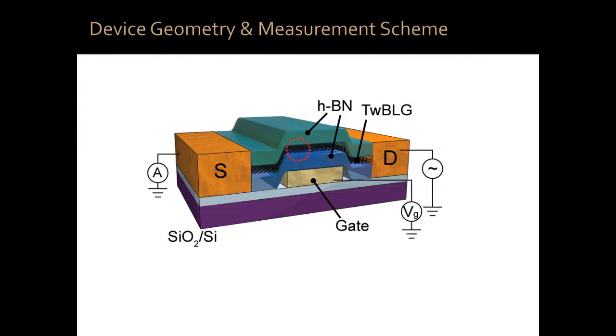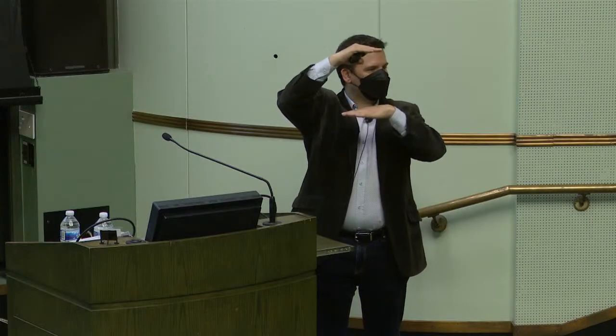You connect it to source and drain electrodes. We have dielectrics on the bottom and the top, and these are just for encapsulation to protect the magic angle graphene. And then it's important that we have a nearby metallic electrode. The metallic electrode and the magic angle graphene form a parallel plate capacitor. So by applying a gate voltage in a field effect transistor geometry, we can vary the charge density in the magic angle graphene. And that's something that we can do electrically.